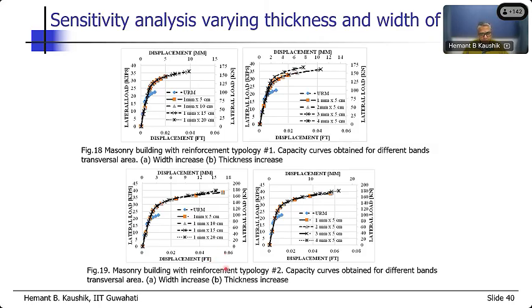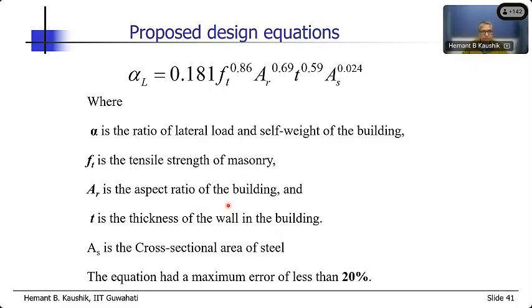In the second method also, the scheme 2 also, whether we increase the width of the band or we increase the thickness of the band, it really did not matter. But if we increase the tensile strength of the masonry, then we have significant variation in the performance. Right? So the conclusion from here is, though we provide very small band, the performance increases drastically. And that is very interesting.